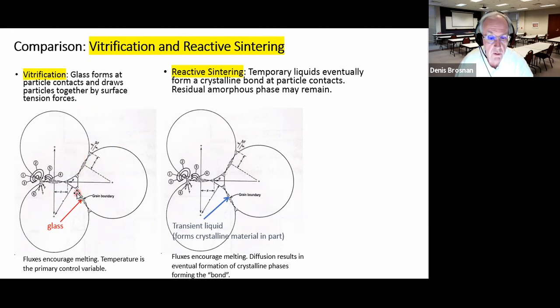Now, spheres have points of contact, and we're illustrating 3 spheres here with 3 points of contact. And what I want to say is, at the point of contact, right immediately at that point is the highest possible surface energy in the ceramic. So the ceramic will act predictably when melting starts. Typically on the exposed surface of the particles, the liquid will migrate to these points of contact, and it will tend to smooth out that point of contact to the point that we get a little radius along the liquid that's formed there. If we stop firing at that point, we can see that on some type of microscope. But nevertheless, vitrification is about forming a liquid phase which tends to migrate toward points of contact in order to reduce the surface energy of the ceramic.